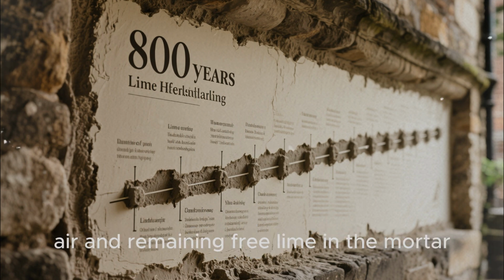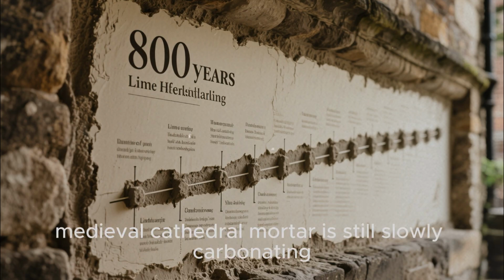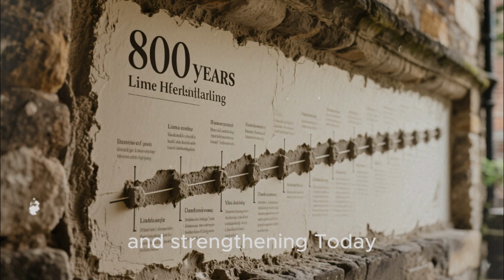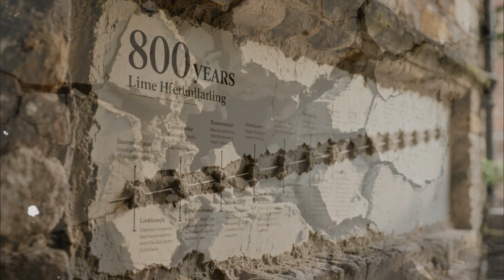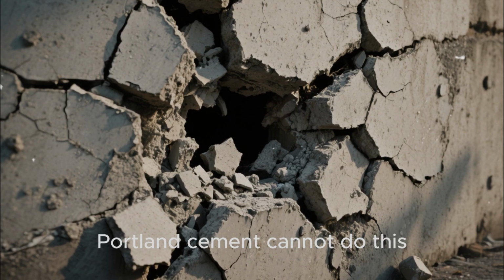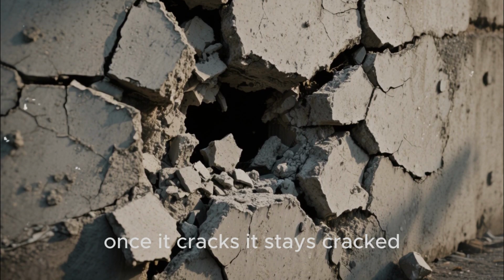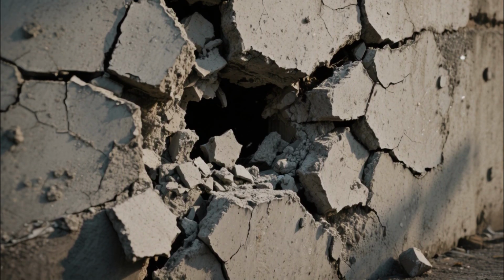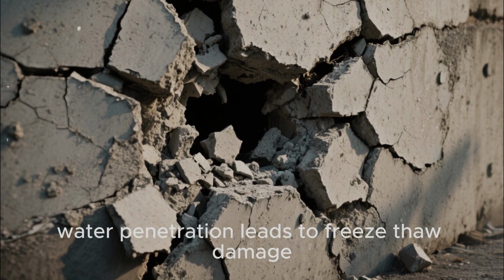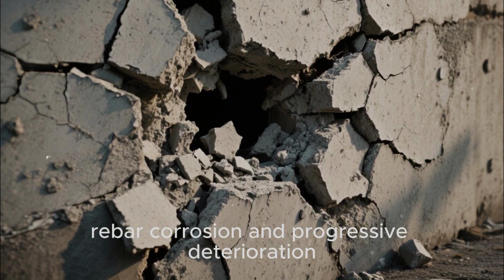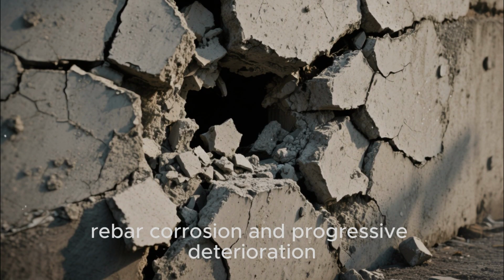This process can continue for decades or centuries, as long as there is moisture, air, and remaining free lime in the mortar. Medieval cathedral mortar is still slowly carbonating and strengthening today, 800 years after it was mixed. Portland cement cannot do this. Once it cracks, it stays cracked. Water penetration leads to freeze-thaw damage, rebar corrosion, and progressive deterioration.